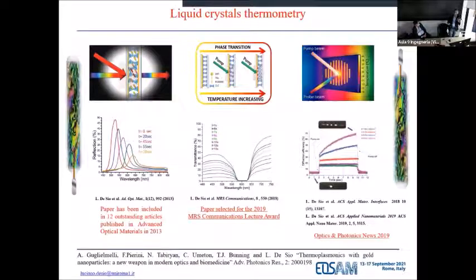It is very important to monitor, to detect, to measure the temperature increase nearby the particles. We started working on the subject, I should say now 10 years ago, when we first combined the unique property of smart materials like liquid crystals and gold nanoparticles. In other words, by using the thermosensitivity of liquid crystals, we were able to demonstrate the capability to measure with very high precision the temperature increase nearby the particle under a suitable laser excitation.